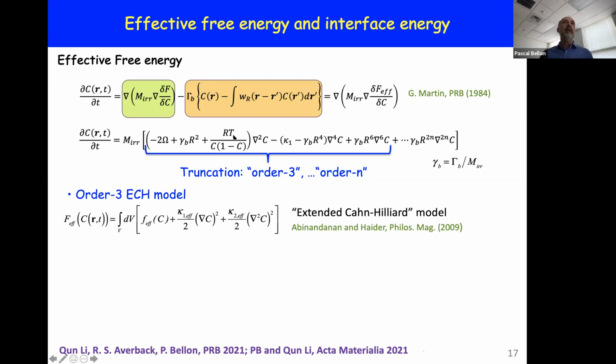So Georges Martin developed a model of an effective temperature, a simple tool that will tell you, under radiation or under severe plastic deformation, the state that the system will reach at steady state in that non-equilibrium environment at low temperature would be the same as if it had been operating at higher temperature at equilibrium. And you just have to look at the equilibrium phase diagram and it will predict the sequence of steady states.